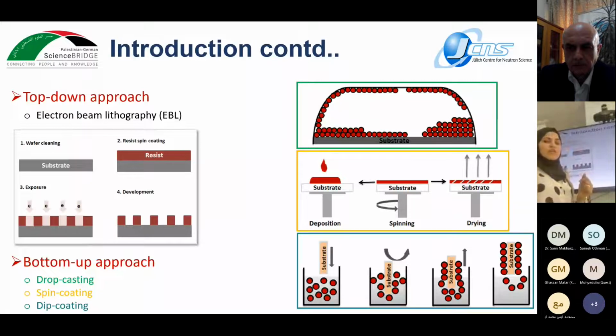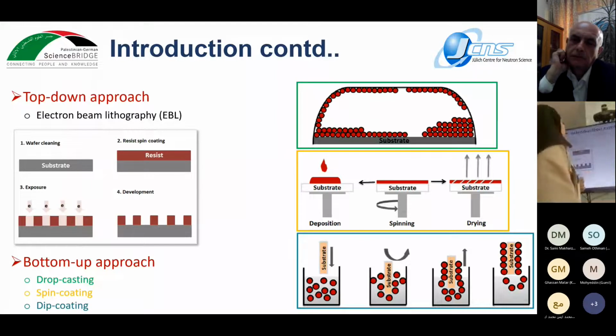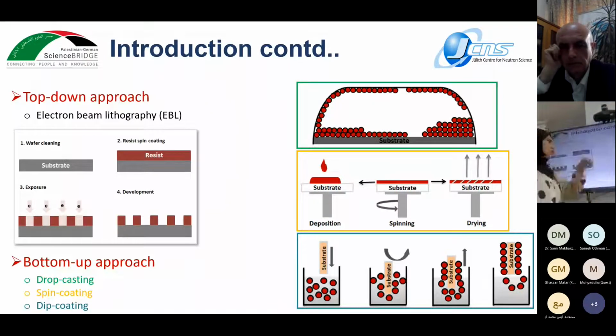So for the third preparation method, I use dip coating, which is a very simple and easy preparation method. We have to care about the concentration of the particles and the withdrawal time of the substrate. That's the idea behind it. We only dip our substrate inside the nanoparticle suspension, and depending on your desired film or desired coil, you can control the time that the substrate stays inside the suspension and the withdrawal time.